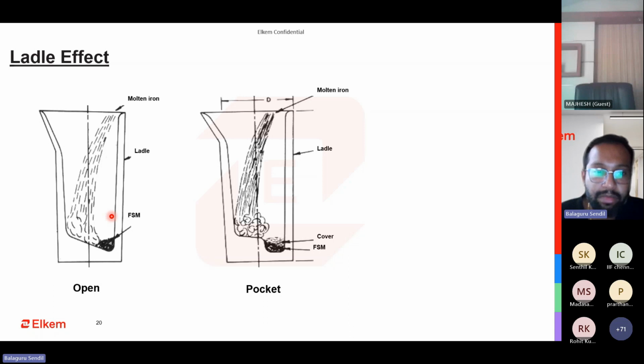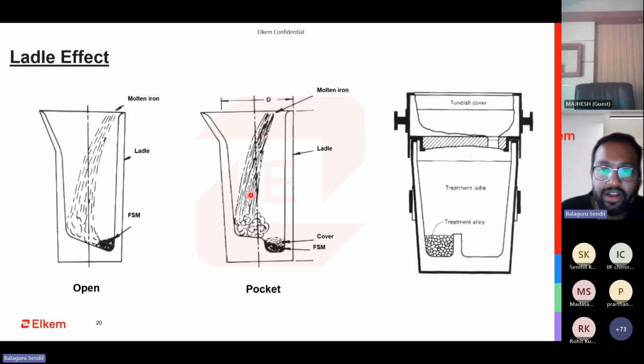But sometimes what happens, people are using more gray and ductile iron. They typically tend to have one common ladle. Most of the gray iron ladles will have a bigger diameter and a shorter height for the ease of handling. In a typical shop floor, it is quite easy to handle. You don't need to have such a high level of shop floor. For ductile iron, it is always advisable to have a tall and narrow ladle. So even in this case, this ladle is an open treatment. This is the pocketed one, and this is the one with a tundish and a proper hole and a pocket alloy cover. So these are the different ladle effects that we are having.